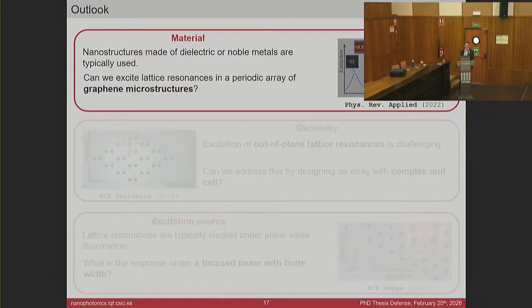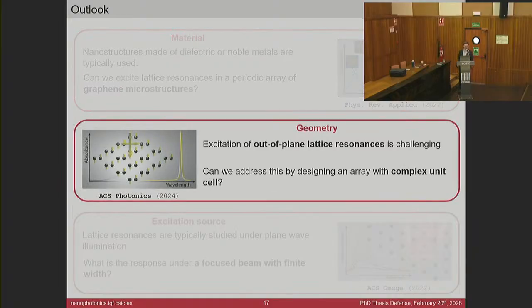So we have seen that we can use graphene as an alternative material to sustain lattice resonances. Now I'm going to focus a bit more on the geometry of the array. In particular, we are going to use the interactions in an array with a complex unit cell with 2 nanostructures per unit cell to solve a problem, which is the fact that if we want to excite a resonance whose dipoles lie out of plane, perpendicular to the plane of the array, then it's going to be really difficult if we can only come with a field that is polarized in the plane of the array.